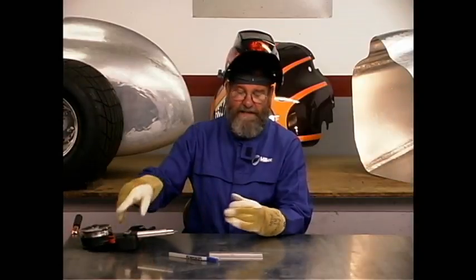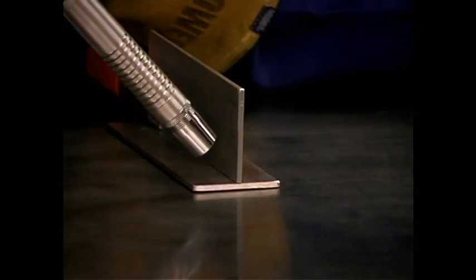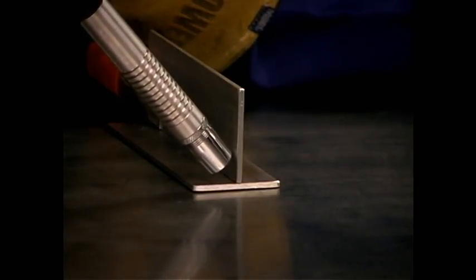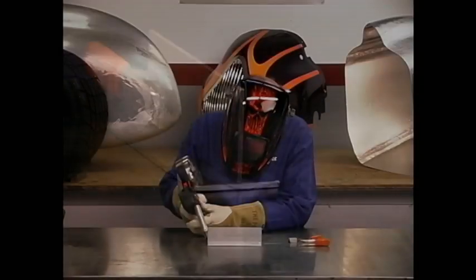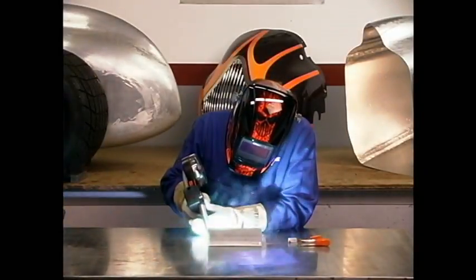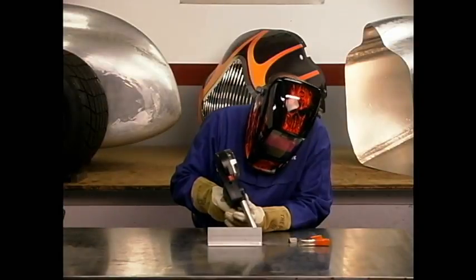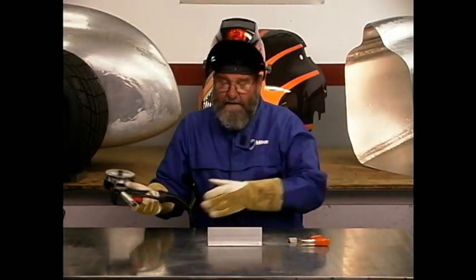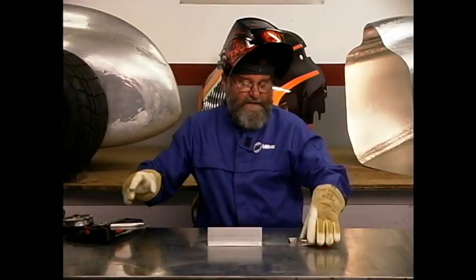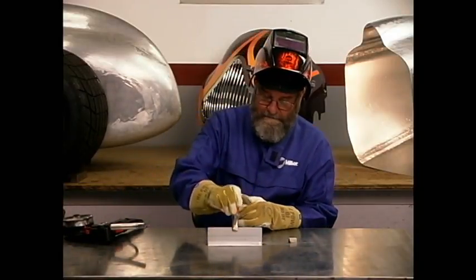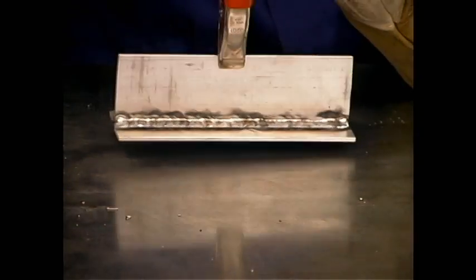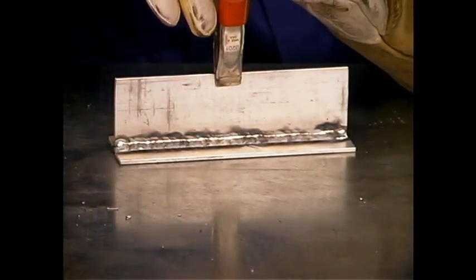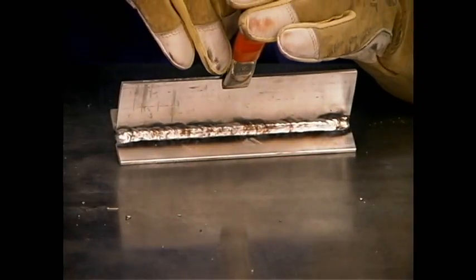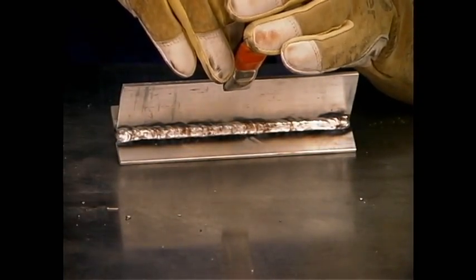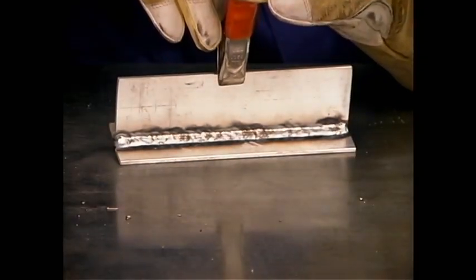Let's get set up to do some welding on aluminum. I'll be maintaining the 45-degree work angle and the 10 to 15 degree travel angle as I make this weld. Okay, so there's our finished weld. I'll spin this around so you can take a close look. Notice how clean and free of defects the bead is. This is a real boon for people who do a lot of welding of aluminum plate, such as building boat hulls, tanker trailers, and many other types of industrial fabrication. There's a little bit of soot on the weld, but that cleans right off with the wire brush.